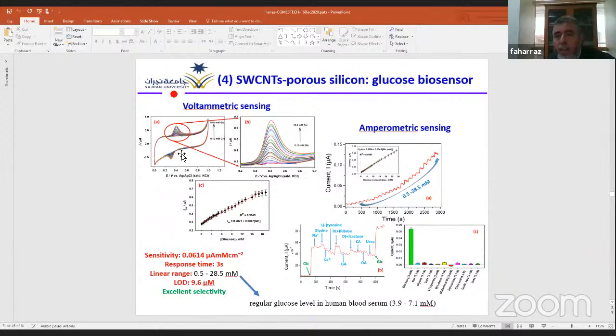Then we examined this nanocomposite of porous silicon with single wall carbon nanotube as a glucose biosensor via two different techniques: amperometric sensing and voltammetric sensing. And we got a very interesting result in terms of sensitivity. Sensitivity here is not very high; it's acceptable, not competitive with the published data, but the interesting point is that the response time of our sensor is very fast, within 3 seconds. We also got a good wide linear range of operation with a very low limit of detection, and the selectivity of our glucose biosensor is actually unique.